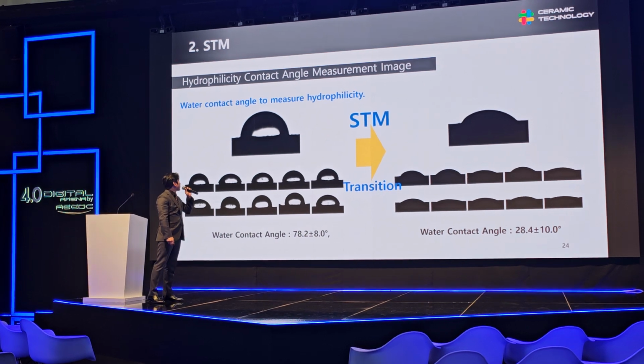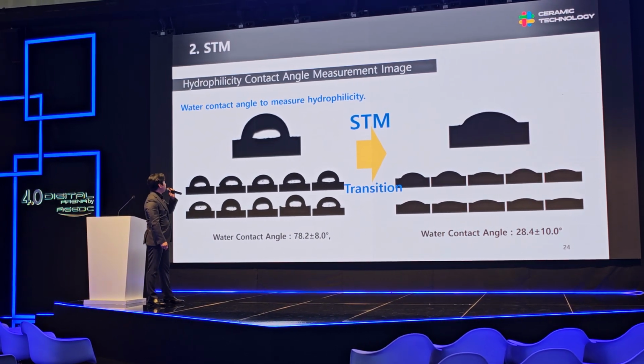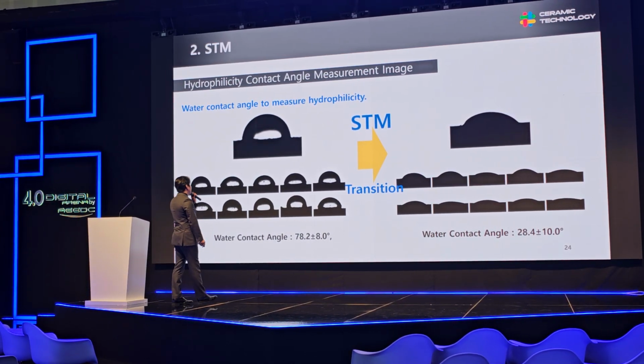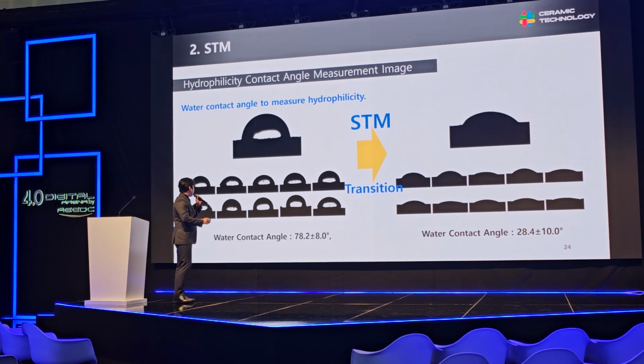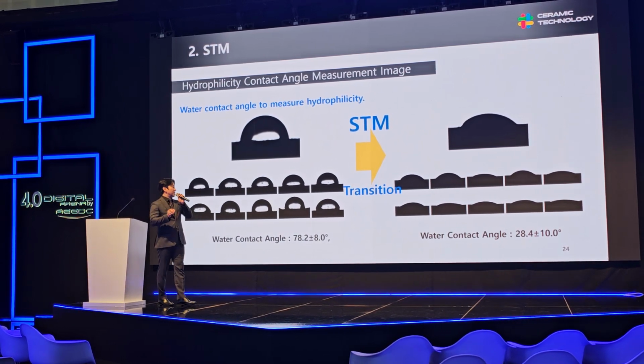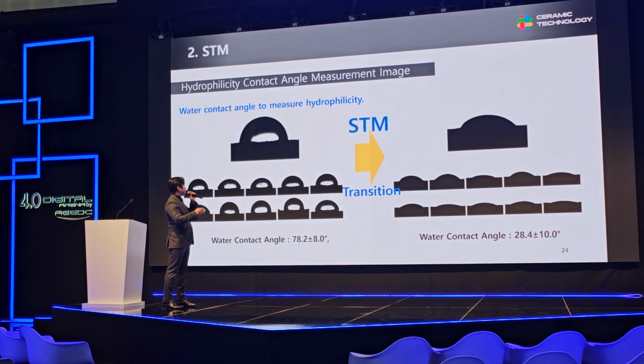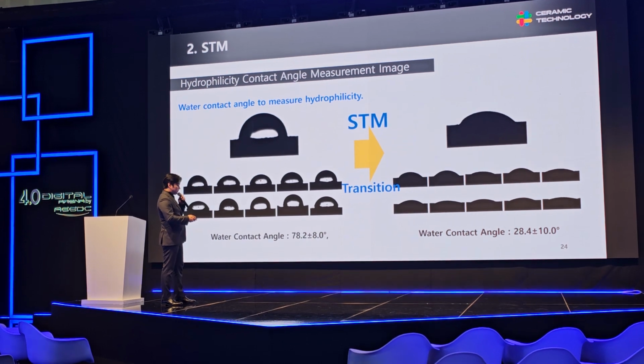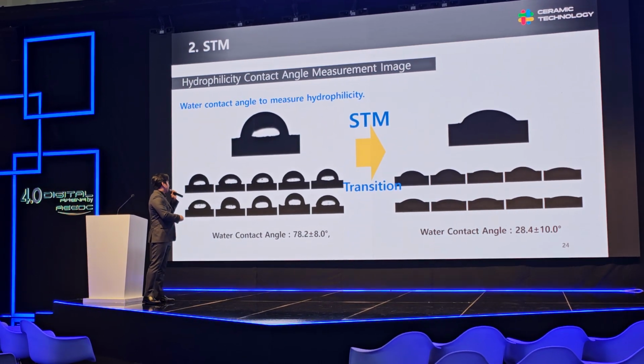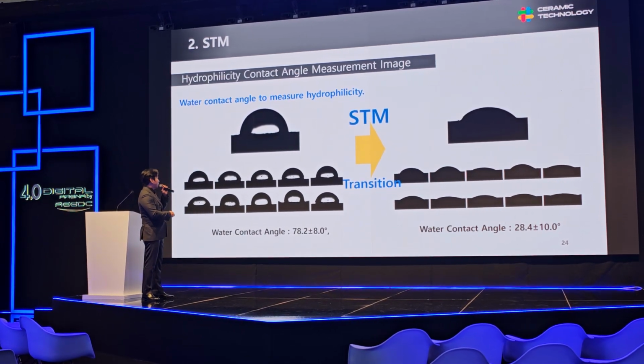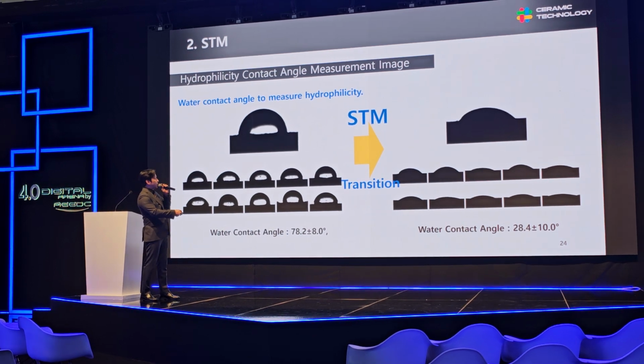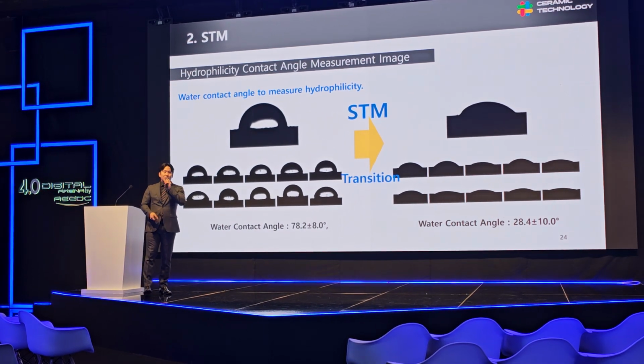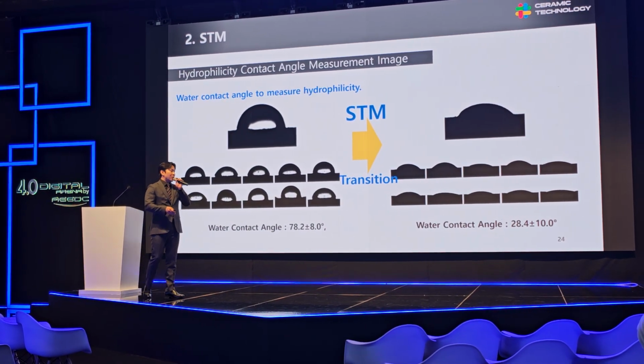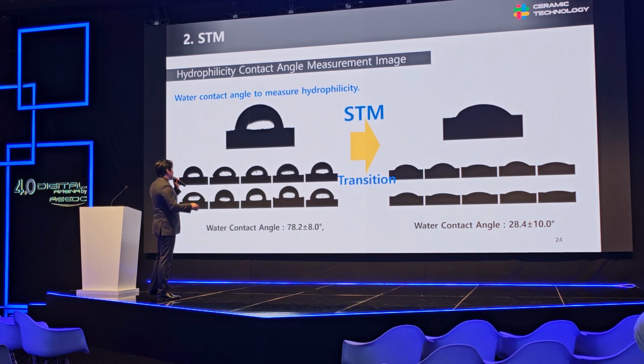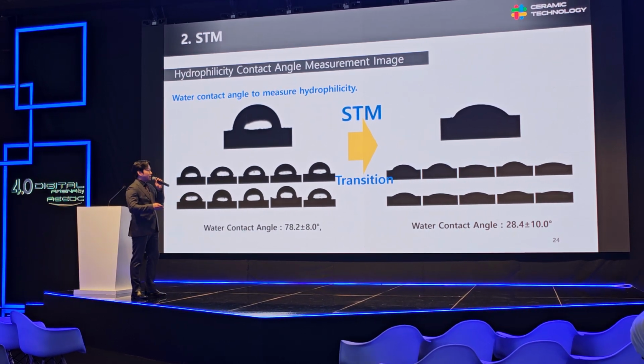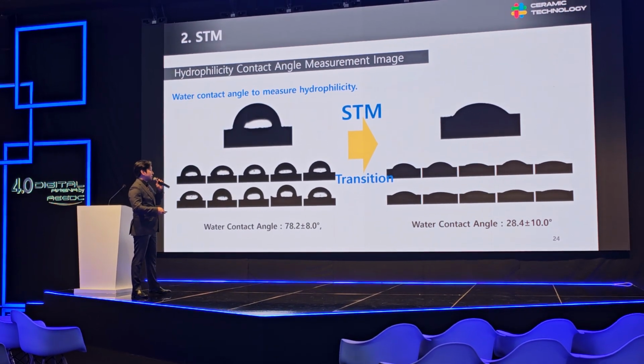And these are the water contact angle images. We measure the hydrophilicity like this. A lower water contact angle indicates a highly hydrophilic surface. So after this treatment, the water contact angle decreased from 78.2 degrees to 28.4 degrees. It means that after this STM treatment, the resin flowability is dramatically increased.